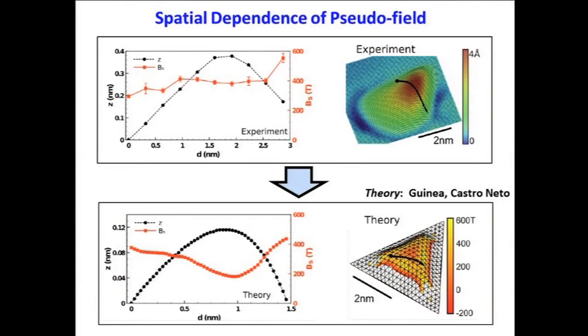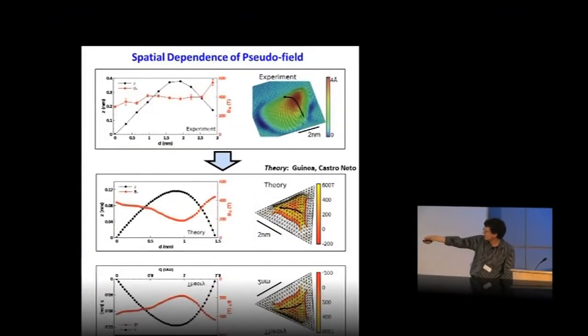Now, in order to further test this interpretation, we did some theoretical calculations in collaboration with Paco Guinea and Castro Neto, and that means that they did the calculations. They used continuum elasticity theory, and they simulated nanobubbles having roughly the same size and strain as the ones that we saw experimentally. And this is the pseudomagnetic field that they calculated, which is very comparable to the one that we saw experimentally. So this is further evidence to support this interpretation.